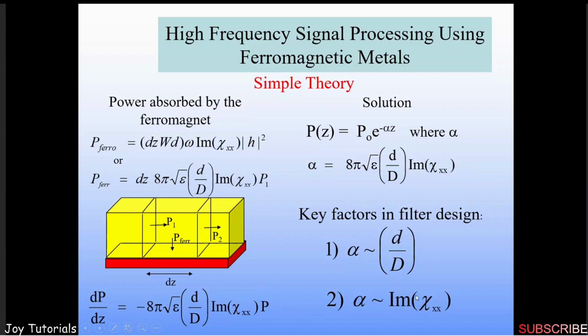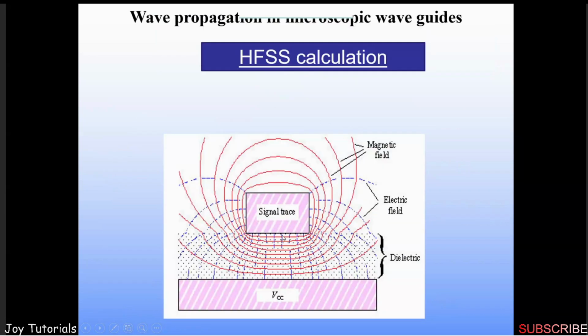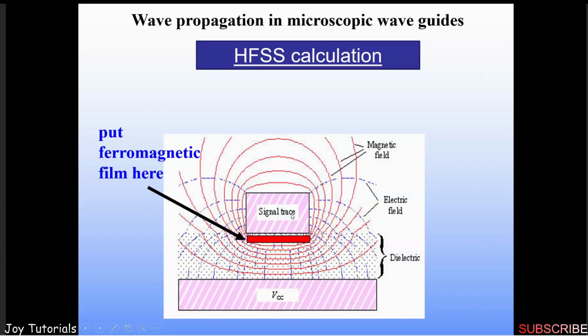Then the imaginary part of susceptibility also comes into the picture when we are designing these microstrip lines. After doing some calculations with the high frequency simulators, we saw that without a magnetic material, the electromagnetic waves are just concentrated below the signal line. What we thought is we can put the magnetic material just below the signal line so that it is going to absorb all the electromagnetic energy and can have an operating frequency that can be tuned from outside.